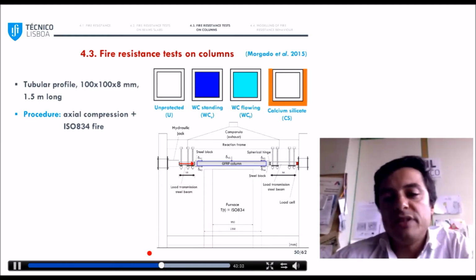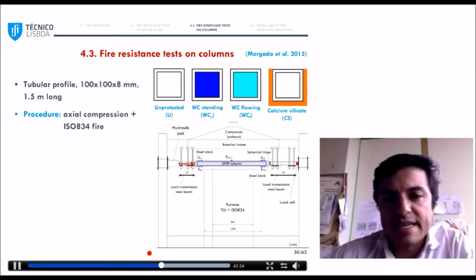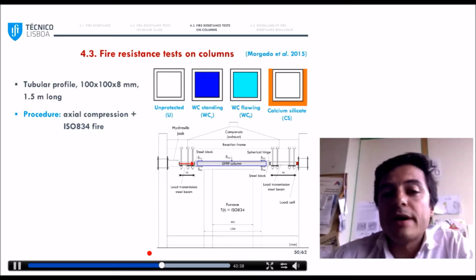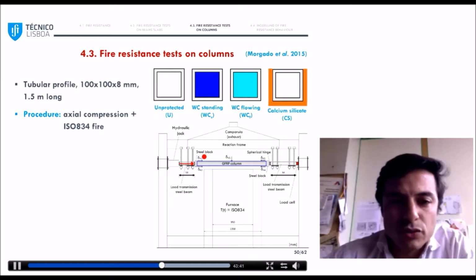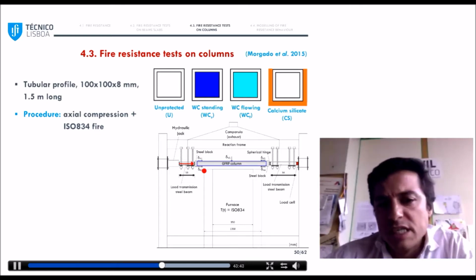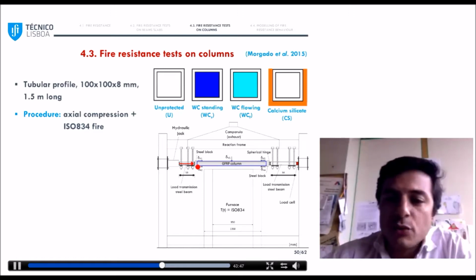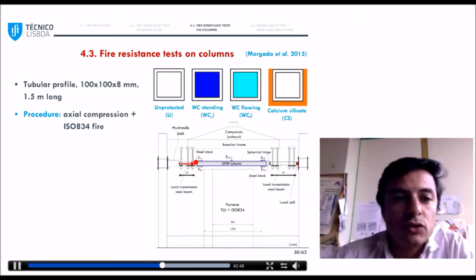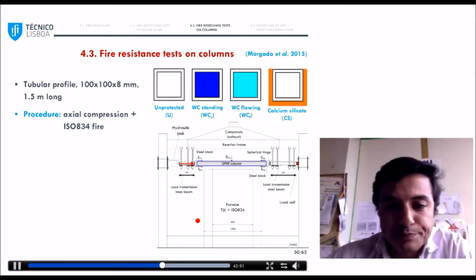So we performed, in this case, similar tests, in similar tubular profiles, but now under axial compression. The setup that you see here is pretty much similar to that used for the beams, except that we now used a hydraulic jack to apply the load.